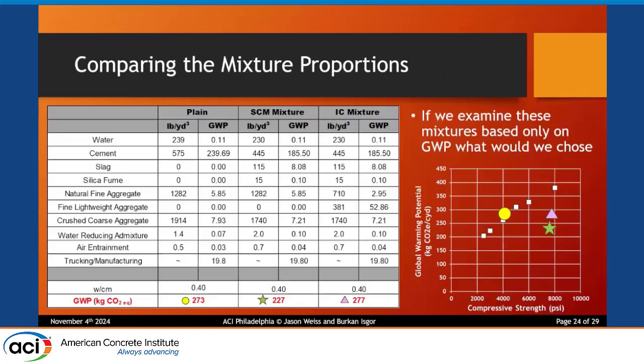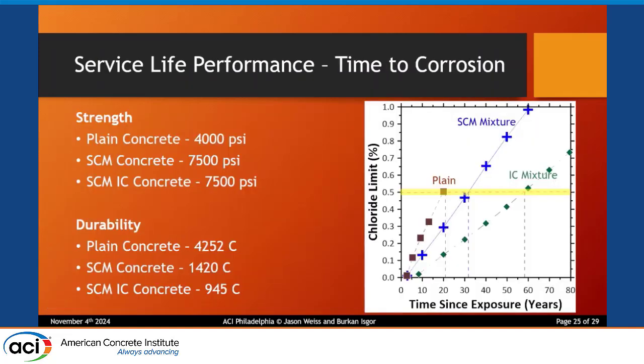So if we take this a step further, all right, what I want to do is I want to come back to this and I want to start to think about some simple ways we could look at these mixtures without having to do the full LCA. Right? And I think there's a little bit of logic if we start to look at this. Now, if we do that computational modeling for those three mixtures I showed before, the plain conventional mix, the mix where we did the slag replacement, and then we did the internal curing, here you see the strength that jumped up, but you also see that we got substantially lower RCPT numbers or substantially reduce transport. When you do service life modeling, that translates into a substantial difference in the time to corrosion.